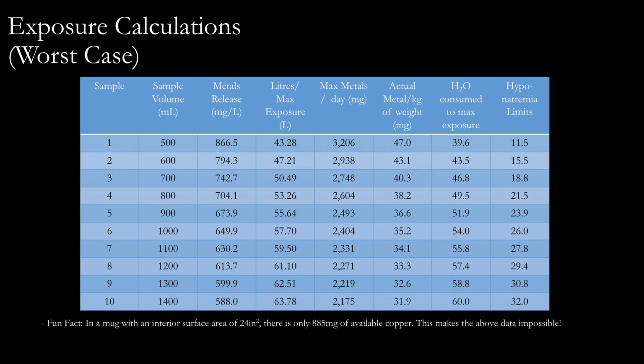These are the exposure calculations in the worst case scenario. I have to pull this up. Wall of numbers, man, every time. So once again, you see the same chart. As the volume increases, your metals release goes down. The liters that you would have to drink to reach your maximum exposure go up. Clearly, with a less concentrated liquid, you're going to have to drink more of it to actually hit any sort of exposure level. The actual metal per kilogram of body weight that you're taking in this theoretical example, our worst case, is only about 47 milligrams per kilogram of body weight. The CDC lists 550. Our worst case, we are nowhere near any sort of danger threshold.